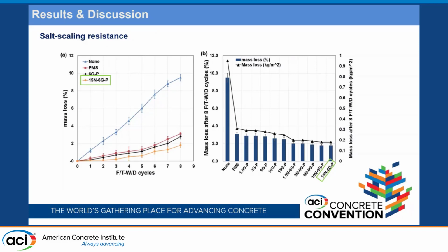So for this test, we prepared some concrete whose quality is not very good, because we wanted it to break very fast. So these 8 cycles, it's hard to say, but if we follow real practice and prepare a very strong concrete, it may be much larger than 8 cycles.